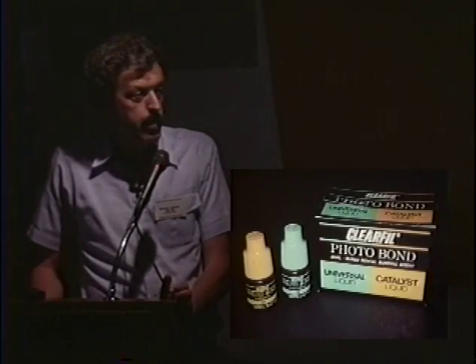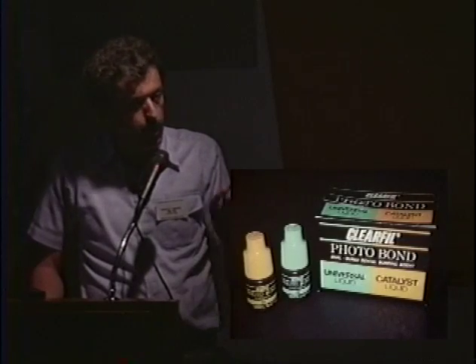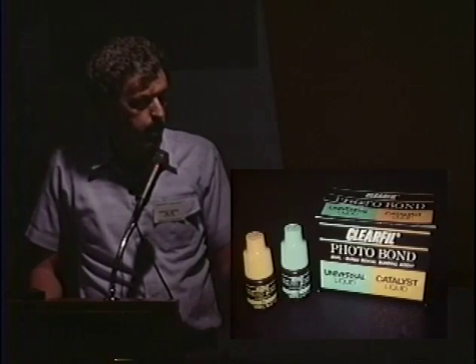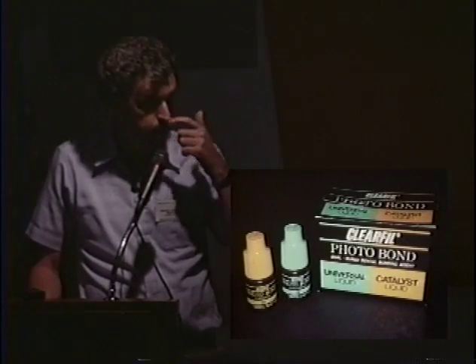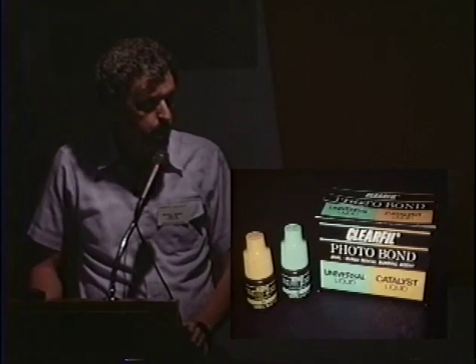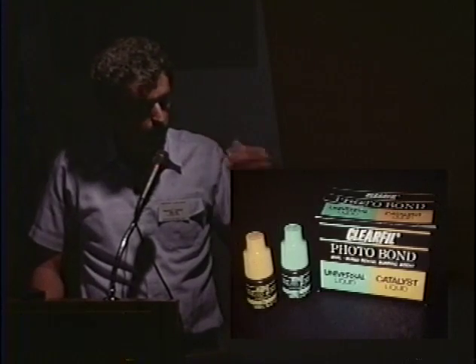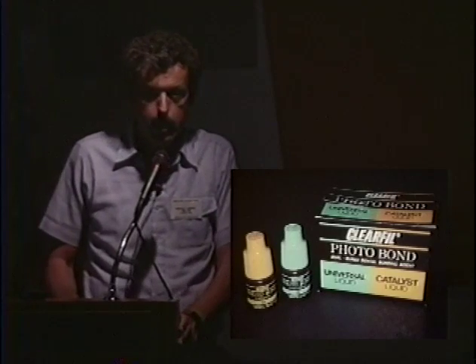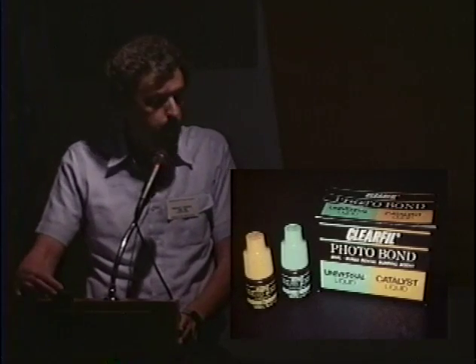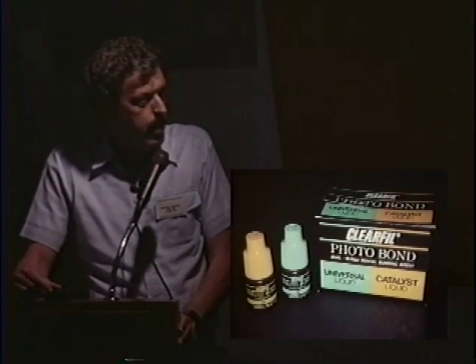Well, that surface scum then is very high in catalyst, so when you put a composite down against the scum, the catalyst in the Photobond sets off the composite and initiates polymerization. It's kind of like a chain reaction. Once you initiate polymerization, it tends to move away from the interface. So that's a very satisfactory way to do it.